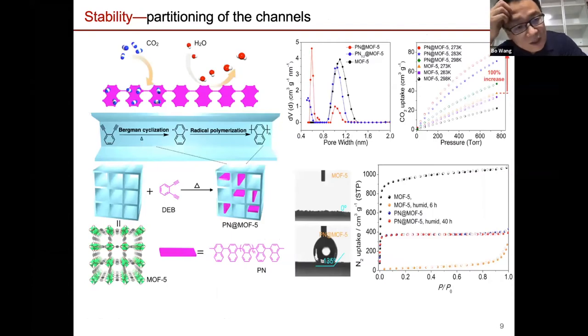And that's one example. Another one is when we're talking about stability. Here, we tried a very simple approach to stabilize some MOFs. In this case, when we take a look at this MOF5 structure, it's very simple, easy to make, and relatively cheap. But the problem, as we all know, is that MOF5 by itself is not water stable. Even when we put it in water, after probably 1 hour or so, you are losing its porosity. Part of the structure is actually collapsing.